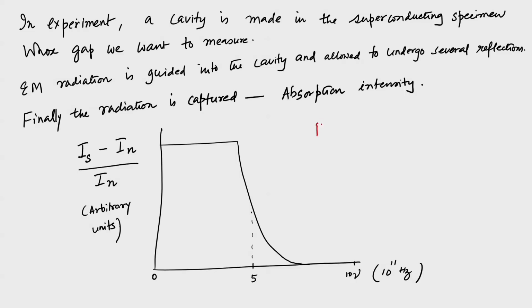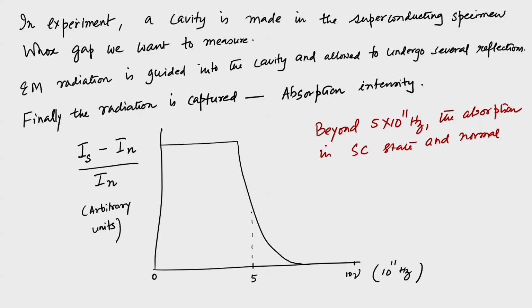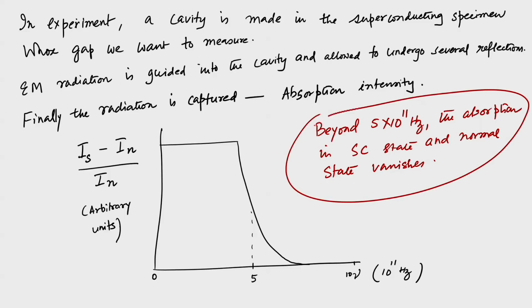To summarize this plot, beyond a certain frequency, which is here, 5 into 10 to the power 11 hertz, the absorption in the superconducting state and the normal state vanishes, which means that there is no distinction between the superconducting state and the normal state, which means that the superconductivity is gone. So, that tells you that there is this frequency which is equal to the gap, and the gap can be estimated from this kind of experiment.